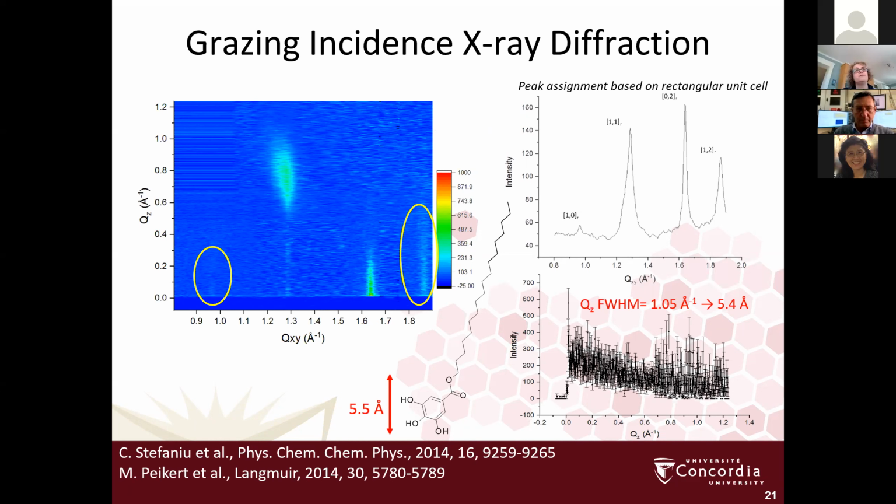And we can't preclude that it's buried underneath, especially with the other evidence we have that suggests a herringbone packing for our chains. Obviously, herringbone packing has been reported for single chain surfactants, usually below room temperature or with much longer chains, about C22 chains, suggesting that our herringbone packing is driven by strong head group interactions.